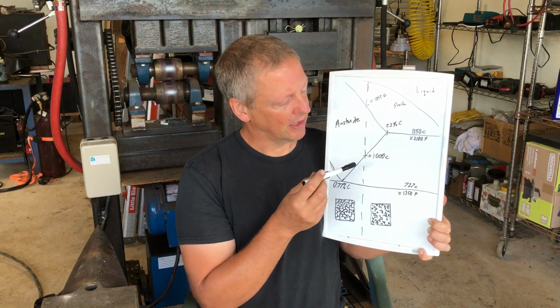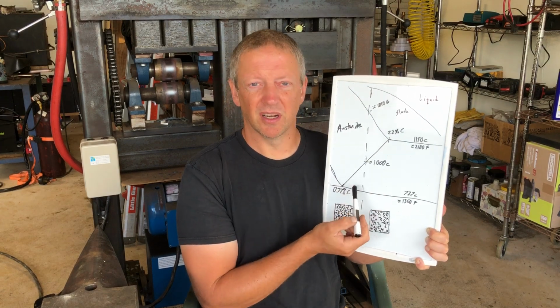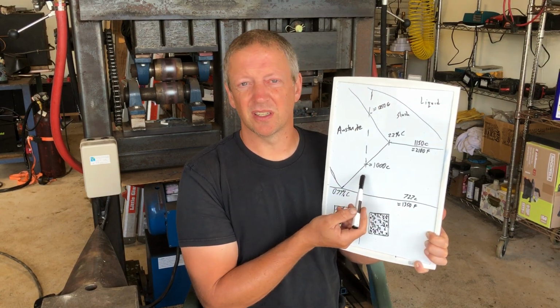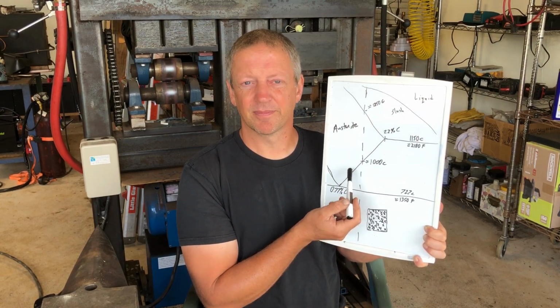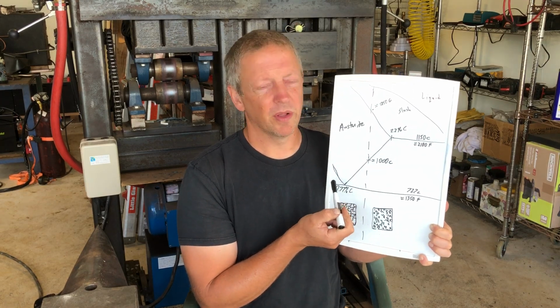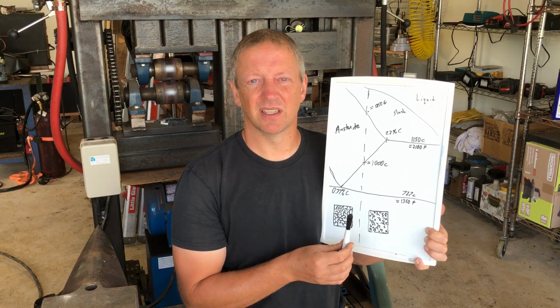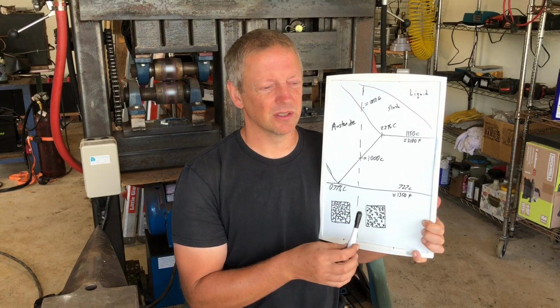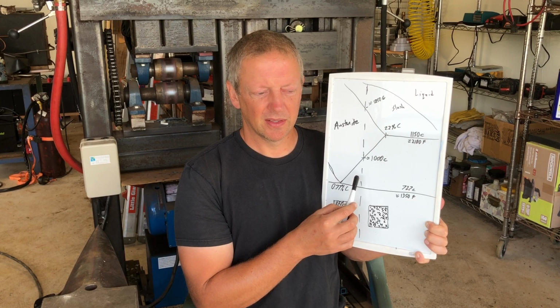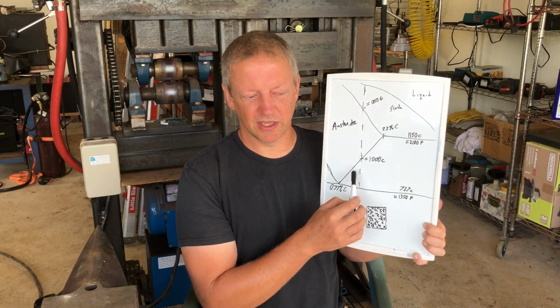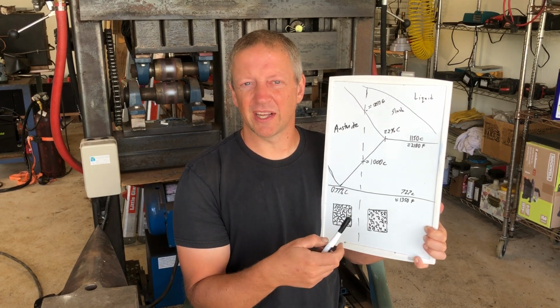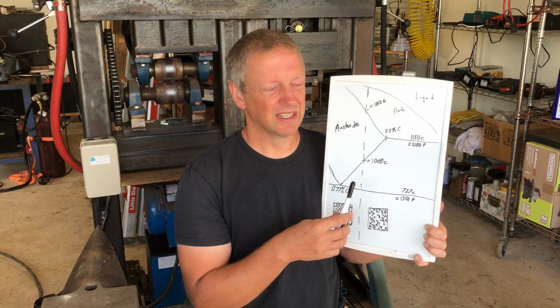Now, if you don't clear the ACM line, one thing that I will note, especially if you have higher alloy material, is that each time you work in this zone, some of your excess carbon goes into solution.